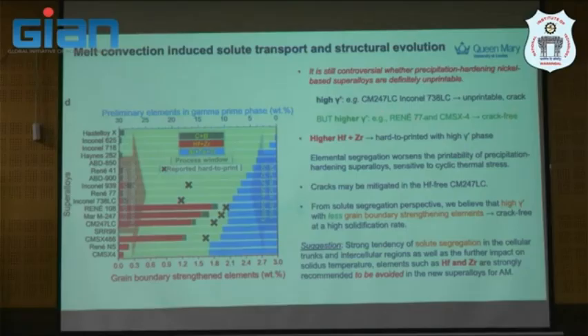Definitely it's probably not the same condition, but this is what we found. It's a bit controversial as well, but that's one of the things that we argue in the paper. Higher hafnium plus zirconium will be hard to print, and this is related as well to the high gamma prime phases in nickel-based superalloy. So elemental segregation worsens the printability of precipitate hardening superalloy, and this will be sensitive to the cyclic thermal stress. And the crack may be eliminated in the hafnium-free CM247.